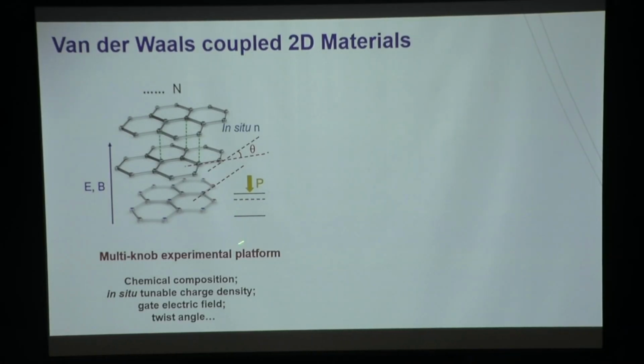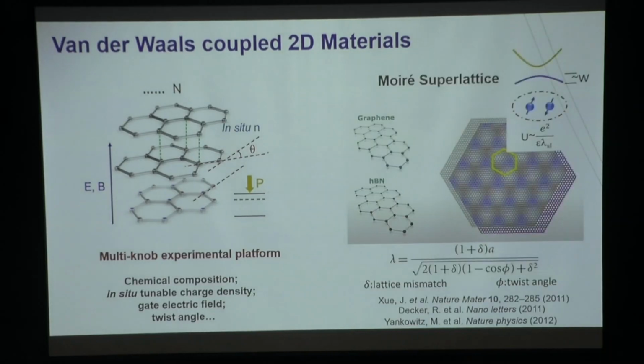And this is still in the 2-dimensional limit. So you can still play this trick of applying a battery voltage to control its charge density and sometimes the band structure. Especially in recent years, this concept of Moiré superlattice has been used a lot in such van der Waals coupled 2D materials. A Moiré superlattice is some kind of spatial beating between 2 patterns. For example, between graphene and hBN, this is one of Mike's early works to first tell people that such large-scale spatial beating could happen when you have graphene on hBN, even at the 0-degree twisting angle, because there's a lattice mismatch of about 2% between graphene and hBN.